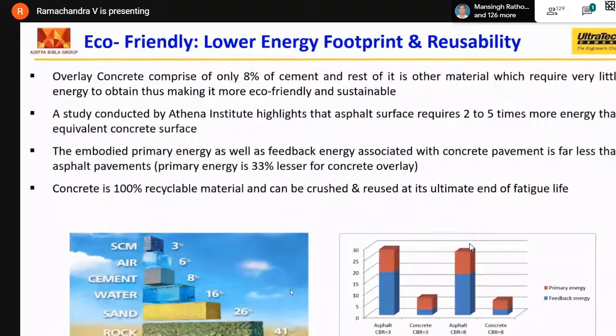Now, a study conducted by Athena Institute highlights that asphalt surface requires 2 to 5 times more energy than the equivalent concrete surface. That means the embodied primary energy in case of concrete is much less compared to that of asphalt. Secondly, concrete is 100% recyclable. Bitumen also to some extent is recyclable, but concrete is 100%. In fact, recycled concrete aggregates can be used once again in making of concrete. As per Bureau of Indian Standards, it can be used in plain concrete and it can be reused at the end of its ultimate life or the ultimate fatigue life.